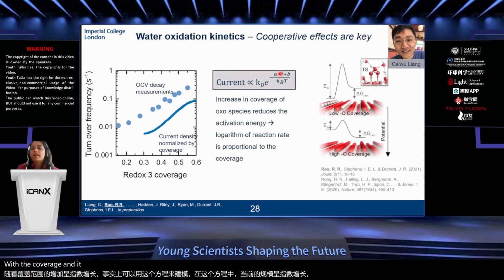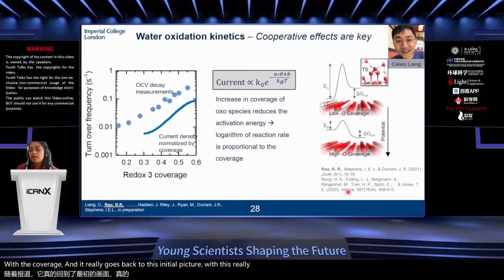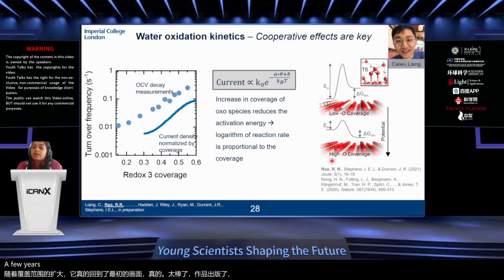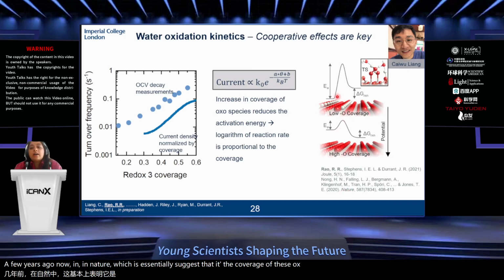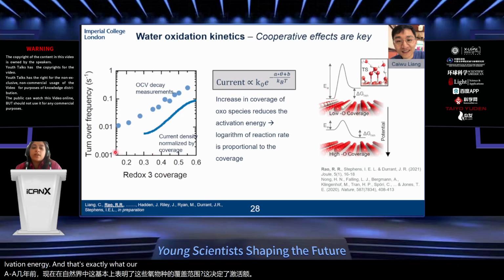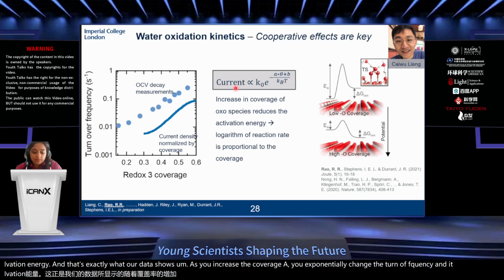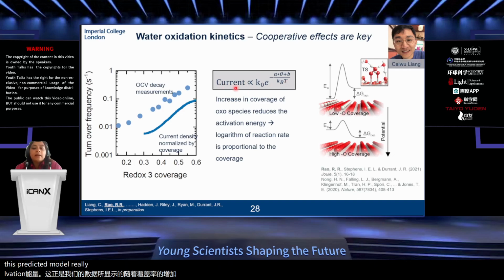And it really goes back to this initial picture with this really amazing work published a few years ago now in Nature, which essentially suggests that it's the coverage of these oxo species that determines the activation energy. And that's exactly what our data shows. As you increase the coverage, you exponentially change the turnover frequency, and it follows this predicted model really, really well.